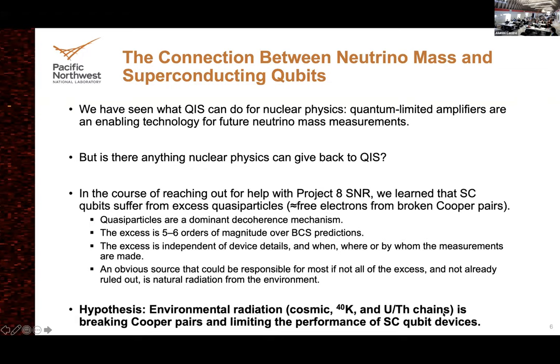He said: these qubits theoretically should have much longer coherence times than they do. They're limited — there are way too many quasi-particles, which are broken Cooper pairs, free electrons. We don't know where all these quasi-particles come from. They're in every device, regardless of material, how you operate them, or who does it. It's universal. Almost everything you could think of that would cause this has been ruled out. One of the only things left that hasn't been ruled out is radiation from the environment — cosmic rays and the radioactivity that's in normal stuff.